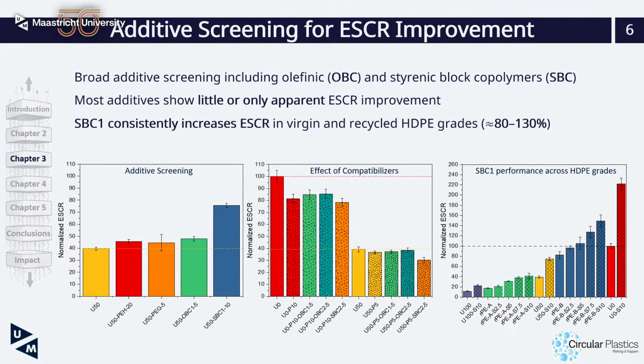In the next step, we try to find an additive that can improve this ESCR and can prevent ESCR loss in the recyclates. We have a lot of different additives in industry, olefin block copolymers, styrenic block copolymers, and most of them work as compatibilizers between HDPE and PP. They can amend the negative effect coming from PP for the short-term mechanical properties, but most of them did not work for ESCR. We just found a styrenic block copolymer that significantly increased ESCR in both virgin grades and recyclates.